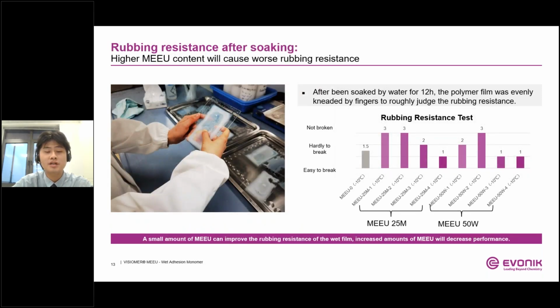And then, after soaking in water, the adhesion of the paint film on the glass plate can also be roughly evaluated in a very simple manner. It's called hand rubbing. The harder it is to destroy by hand, the higher the score. If you see the chart on the right, it can be seen that 1 to 2% MEEU 25M and 2% MEEU 50W samples performed best, proving it improves the wet adhesion.